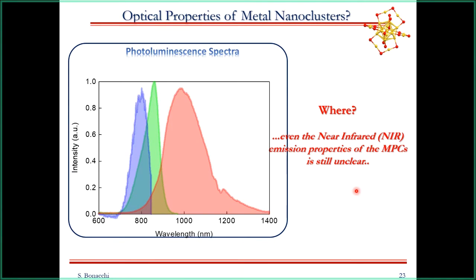Just to explain why there are so many, in some cases even mistakes or doubts, about the photoluminescent properties of this cluster, I would like to show you these three different emission spectra. If you look at them, they look like the emission of three different species, but instead they are the emission of the same kind of gold 25 cluster, obtained by using the same fluorimeter but just playing with three different photomultipliers. This example shows that since the emission of gold nanoclusters in general is in the near infrared region, you surely know that this region is very hard to detect. And if you don't use the proper PMT detector, you can see different maxima, different shapes, just because you are using, let's say, the wrong eyes to observe your cluster.